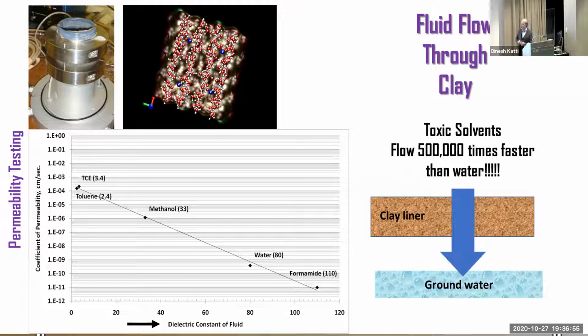So on the horizontal axis of this plot, you see the term dielectric constant of fluid. Now, what we found from our molecular dynamics simulations is that as the dielectric constant of the fluid increases, as you go higher towards the right, the strength of the molecular interactions between the fluid and clay increases. So for example, here the water and formamide fluids have very strong molecular interactions with the clay. On the other hand, if you go on the left side of this axis, when the numbers become small or zero, the molecular interactions between the fluid and the clay become very small or negligible. So for example, when you see TCE and toluene, the dielectric constant is very small, and the molecular interactions between the fluid and the clay are negligible or very small.